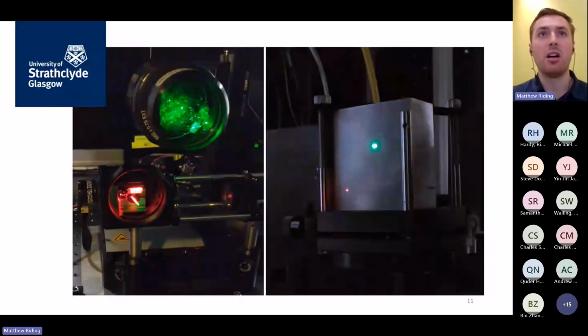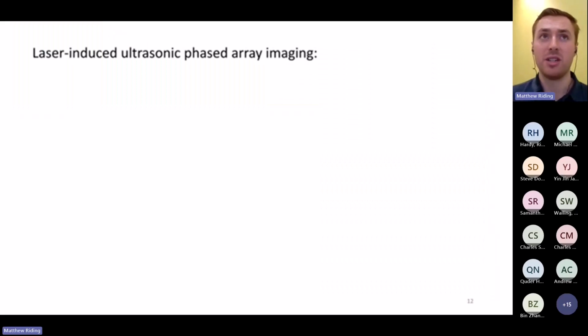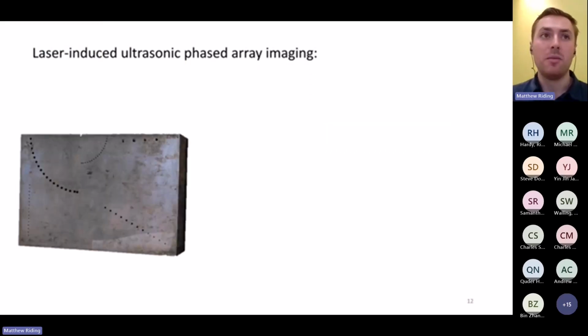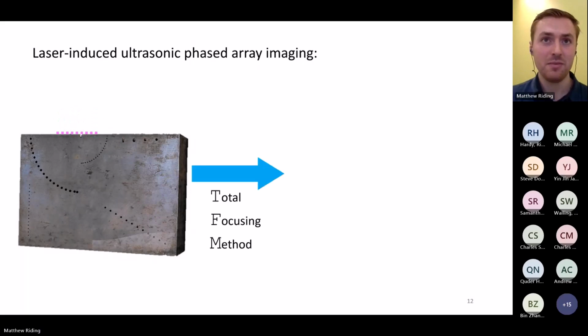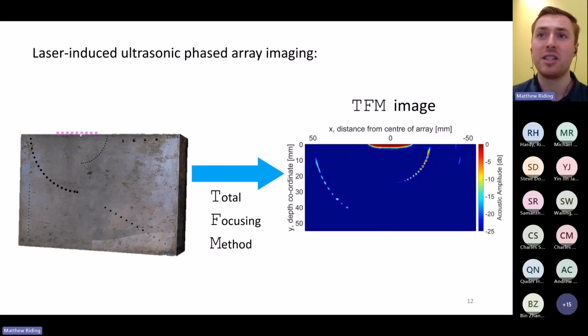So this brings me on to the idea of phased array imaging using laser-induced ultrasound. Using our assembly, we can position and scan our lasers over the surface of a sample and capture A-scans in a process known as full matrix capture. This is to synthesize a phased array in post-processing. We apply a standard ultrasonic imaging algorithm known as the total focusing method, and that allows us to generate ultrasonic images of the subsurface reflectors inside our samples.